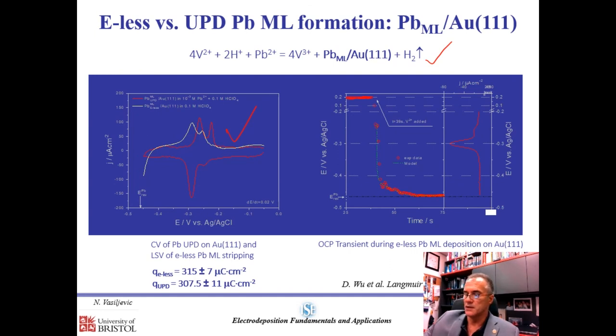If you look at the open circuit potential when you introduce the vanadium into the lead-containing solution, for example for the gold surface, it drops and stabilizes a few millivolts above the lead reversible potential, which means that all the time your open circuit potential is in the underpotential range for lead, where only a lead monolayer could be stable. And just to give you a pictorial description, you see here the lead UPD wave from the other picture, and you can see that the open circuit potential drifts through the region where the monolayer of lead forms on the gold surface.